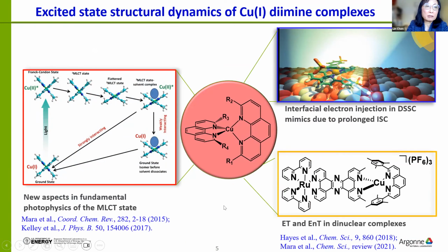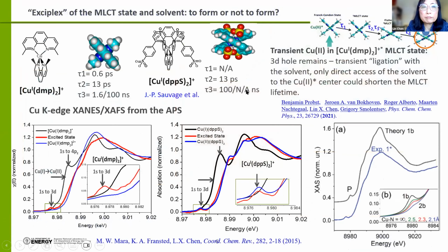Yeah, so we did extensive photophysical studies using both laser and X-ray, and that sorted out the different lifetimes and different structural changes, and I'm going to mention that later. And that evolved into using the copper complex as the light sensitizer dye, like those ruthenium dye molecules in the dye-sensitized solar cell model system, injecting electrons into TiO2, and then developed into multiple metallic systems doing photo-induced electron transfer from one metal to the other. So fundamentally, the copper complex is very interesting with a lot of really significant signatures in the XANES region as well as the EXAFS region. So I'm going to talk, focusing on the pre-edge in this slide.